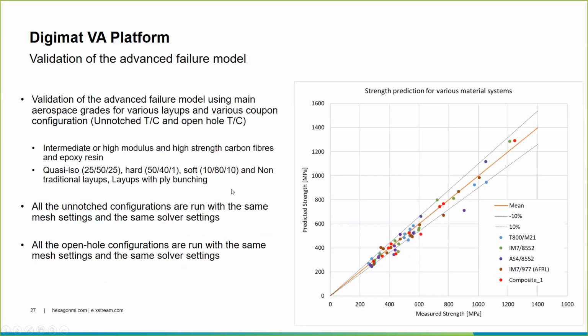And so one thing that I have not mentioned so far is that all those tests, all those values, have been obtained with exactly the same configuration for the unnotched test. So all the unnotched tests here, no matter if tension or compression, have been run with the same mesh settings and the same solver settings. And that's the same for the open hole. All the configurations, tension, compression, have been run with the same mesh settings and the same solver settings. So it means that the default mesh settings that I have shown just before have been used and have not been changed from one configuration to another. We don't need to change the mesh settings if we are dealing with a hard layup or soft layup. There's no such rule. We just use the same mesh settings, no matter the layup and no matter the test.